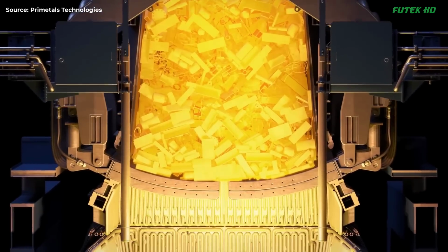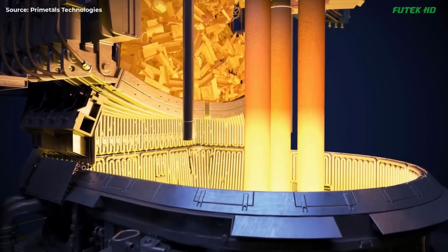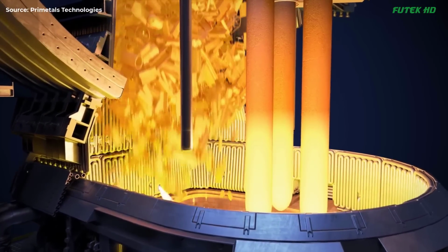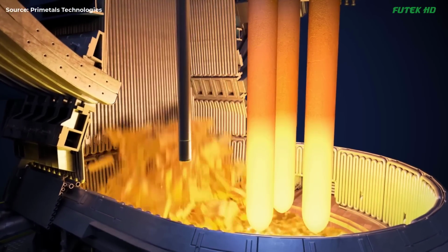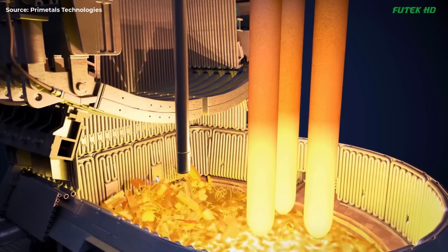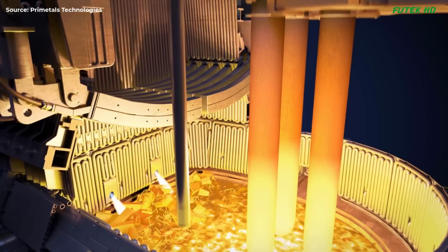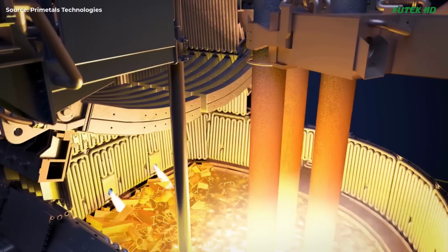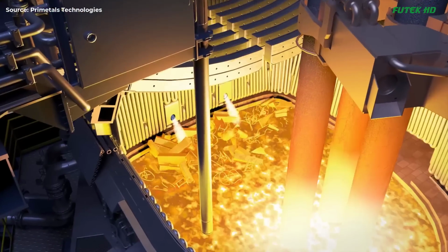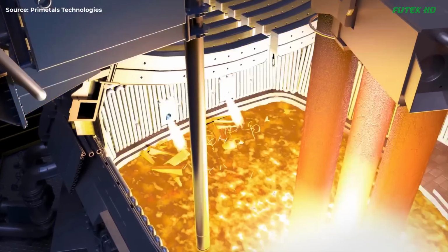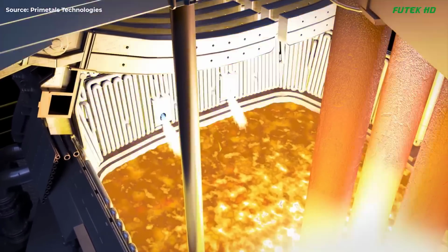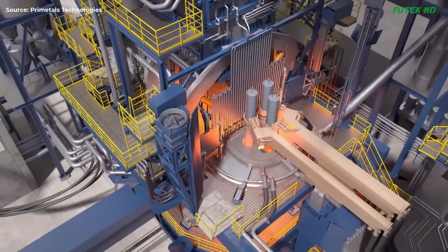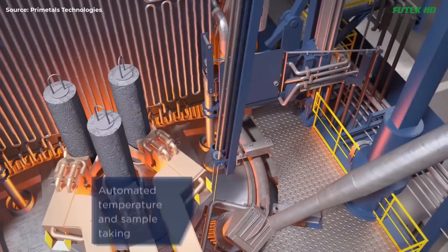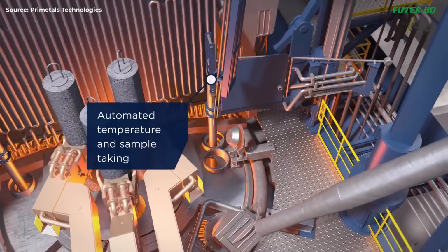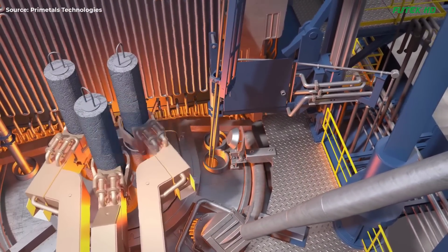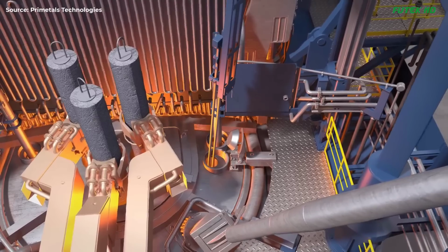High energy efficiency. One of the standout features of the EAF Quantum is its ability to preheat 100% of the scrap, which significantly lowers energy consumption. The furnace achieves energy consumption rates of less than 280 kilowatt-hours per ton of steel, making it one of the most energy-efficient electric arc furnaces available. This efficiency is achieved through the innovative design of the furnace and the effective use of recovered energy from the off-gas.